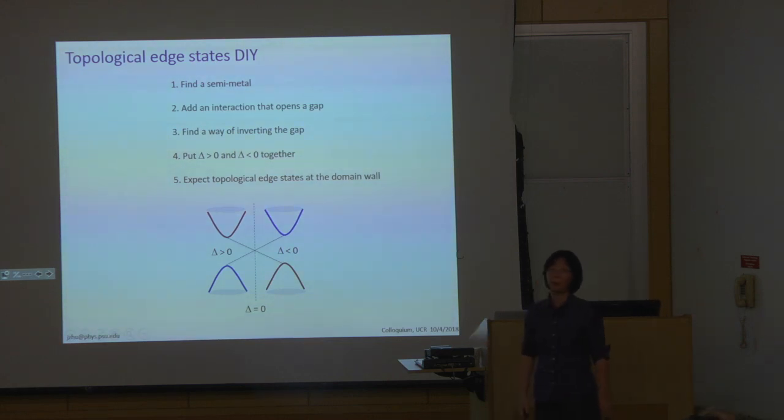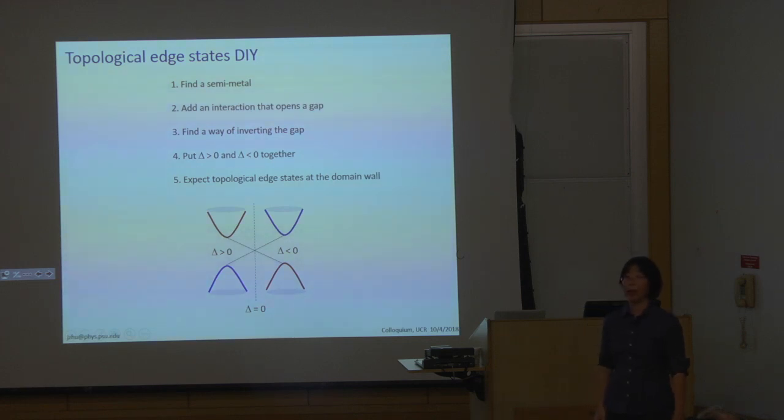So let's start from a material with zero gap or a very small gap. If you start with something that has a 2 eV band gap, your interactions are not that strong. You can't invert that gap easily. And that's why topological insulators are narrow gap semiconductors. You don't find them in something like molybdenum disulfide. Right? Okay.